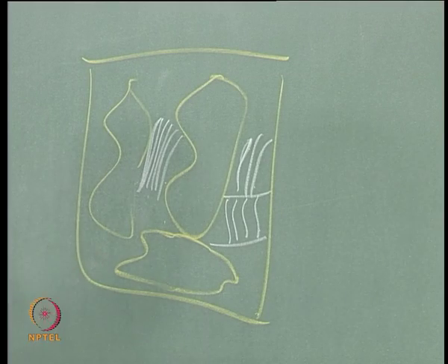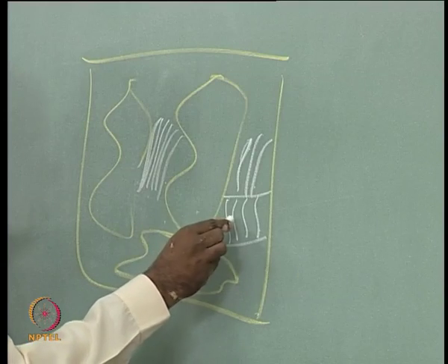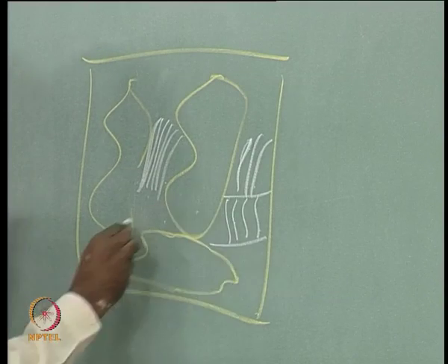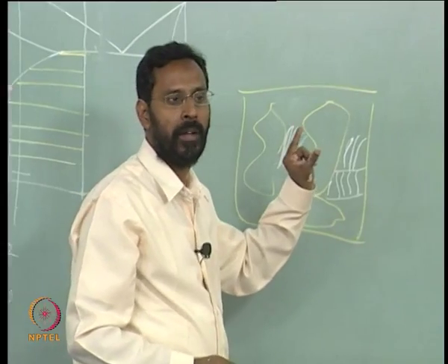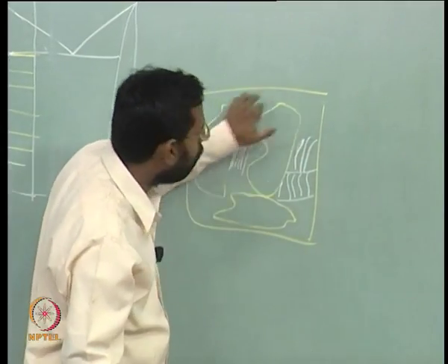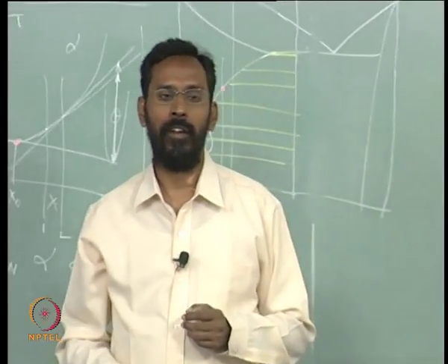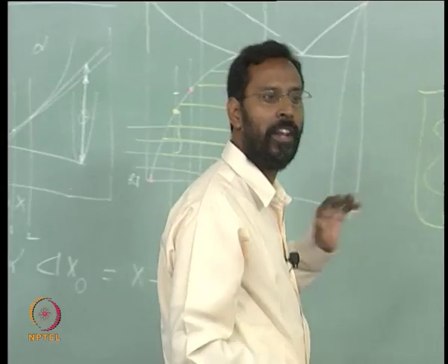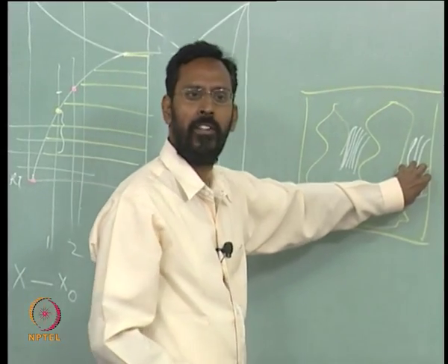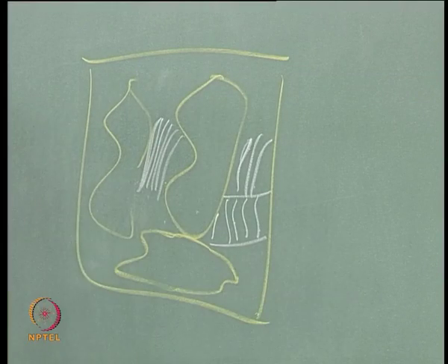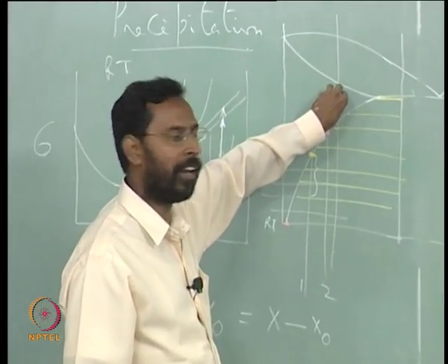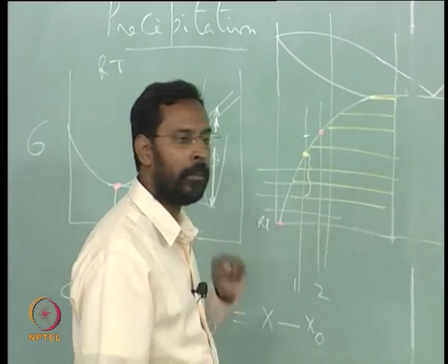And for example, copper that is coming out will not go and precipitate on this theta, because it has to travel a farther distance. So, in principle if there is a theta which is already available here, that theta becomes thicker, or the theta will form as a layer on the existing alpha. So, you will have two morphologies of theta, one theta which is already present in the eutectic mixture, and second the theta which is there at the grain boundaries, or the dendrite boundaries if you want to call them. Whereas in this case you have the alpha coming out as the grains after the solidification, and the theta precipitation is only there.